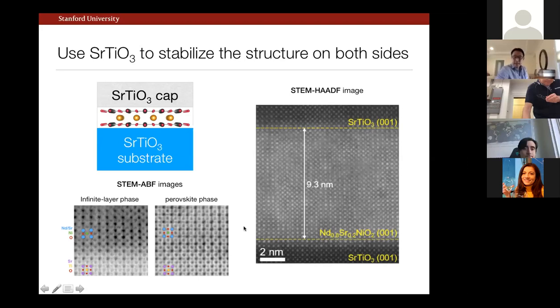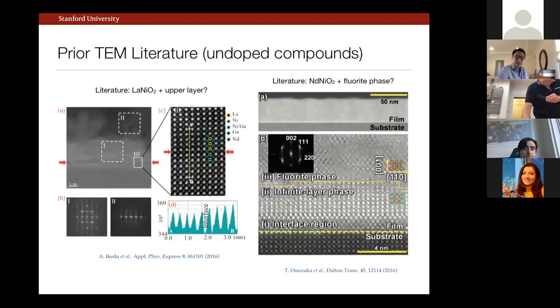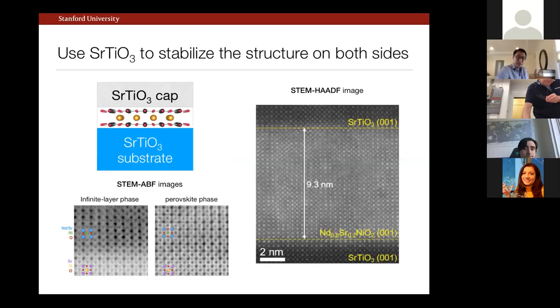So yeah, that is also currently the limitation of what we have in terms of a typical maximum thickness of sample. It is rather restrictive, unfortunately, that we're limited to this 10 nanometer scale. And going back to this prior work, you can easily imagine that basically there is some length scale of a few nanometers from the interface where we can have this kind of proximate stabilization. And so you can roughly double that, but going beyond that, what will happen is these sorts of secondary phases will appear kind of in the midst of the film. Okay.